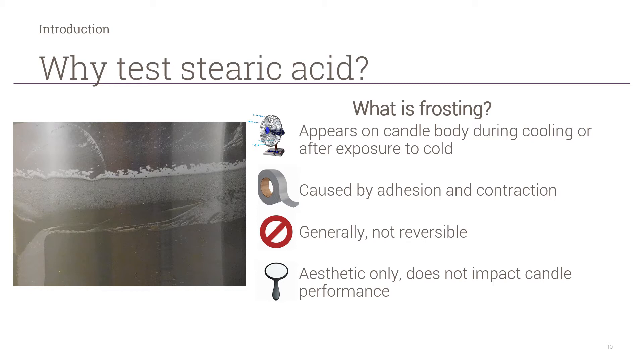The first defect is frosting. Frosting appears on candles during cooling or after exposure to cold and is caused by adhesion and contraction. It resembles frost on your car windshield in the winter. As the wax pulls away from the glass, it can leave a film, and we refer to this as frosting. It's not reversible and it doesn't impact the candle's performance or its safety.